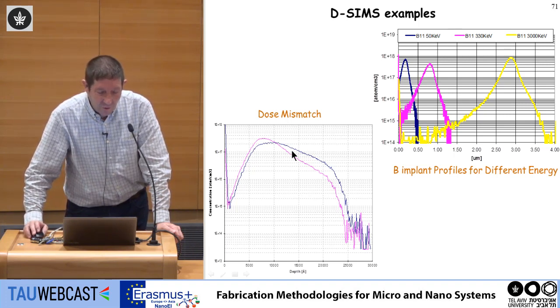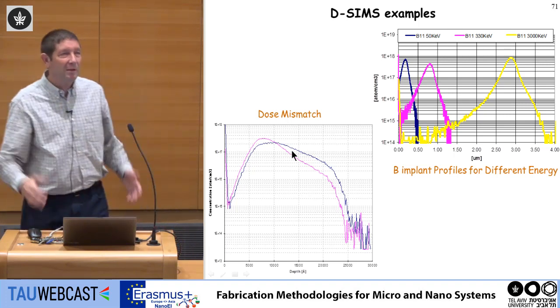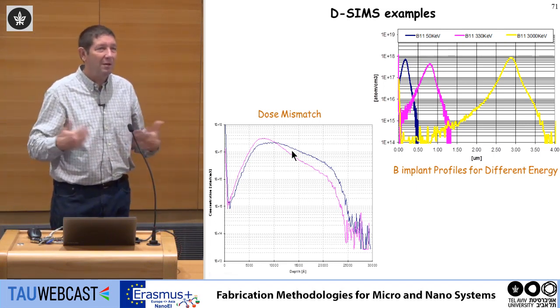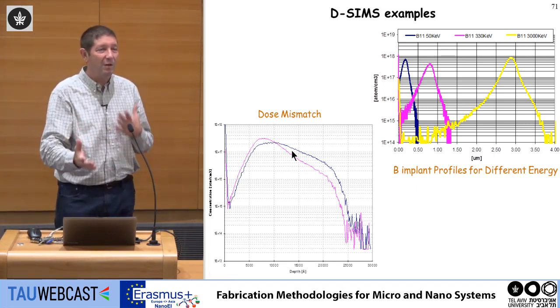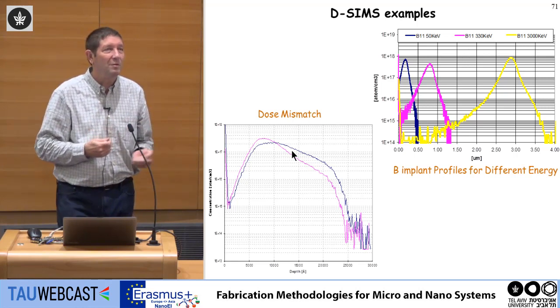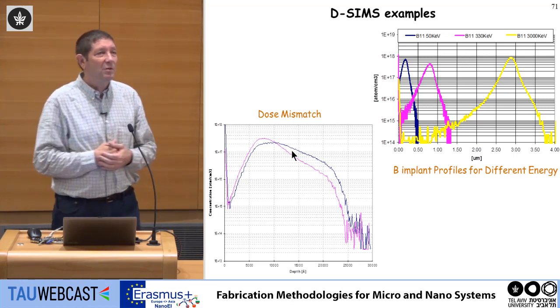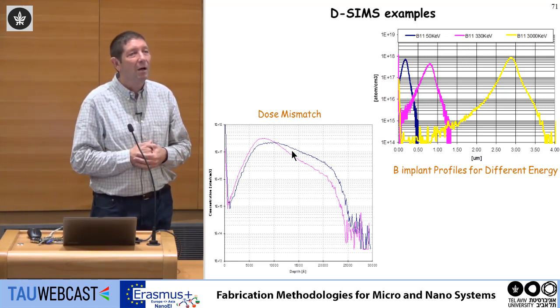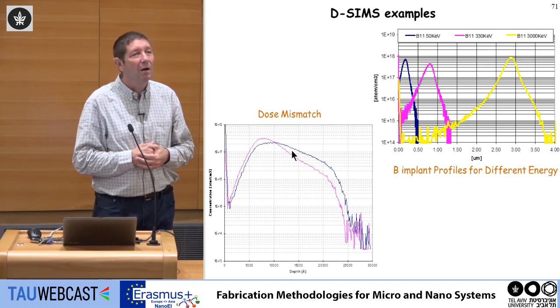And by the way, this is dose mismatch, which means I take a wafer, implant, take another wafer and implant, and measure the profile. It shows you there's some mismatch between the wafers. Questions? This method is destructive to the material. Yes.